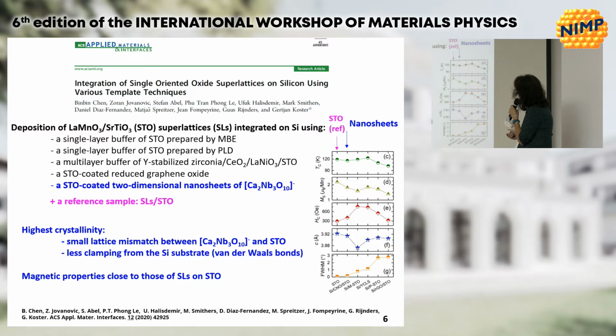And here are the results. They have shown that if we compare the superlattice films deposited on nanosheets with the reference, this is the best result in terms of all properties. I mean crystalline properties and also magnetic properties. And this is due to the small lattice mismatch between these nanosheets and the strontium titanate, and also to less clamping from the silicon substrate.